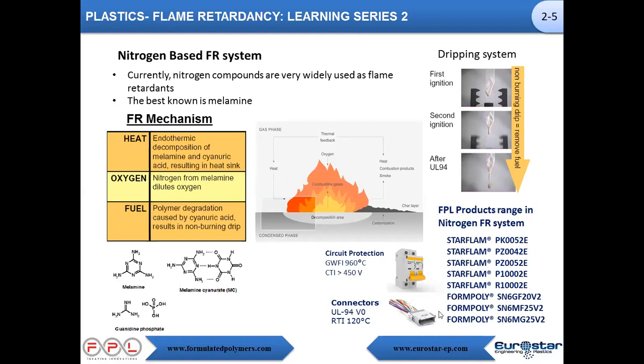From this, we have a very extensive range, in Eurostar or in FPL, and you can find unfilled material, filled with fiber, with mineral, with wollastonite, with mixes, based on different polymers, 6 and 6,6. So this is a very nice and up-to-date range with V0 down to very low thickness and a good RTI.